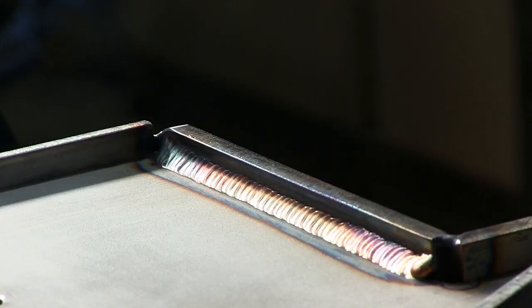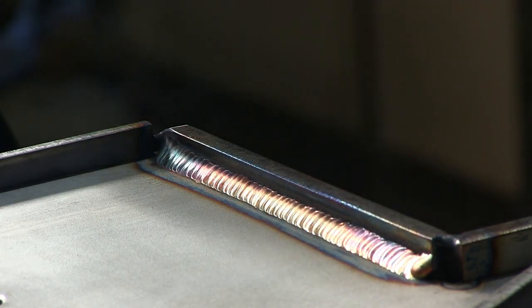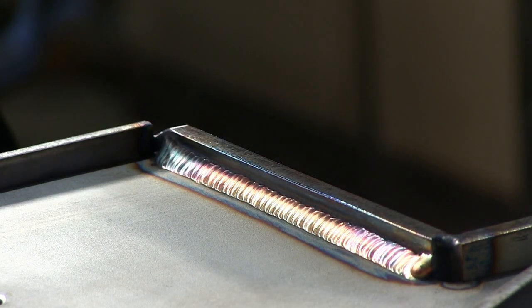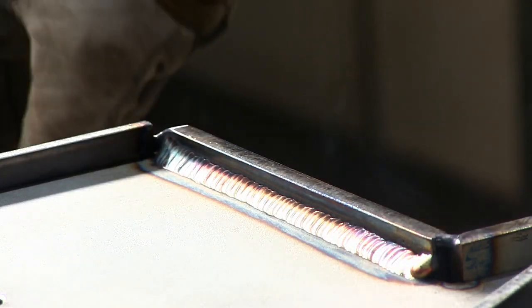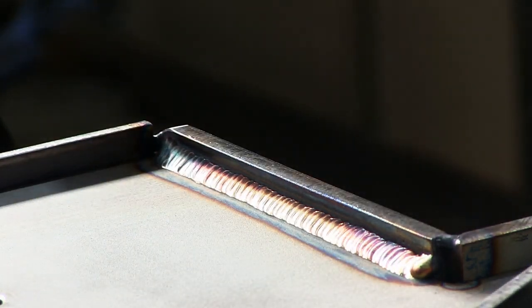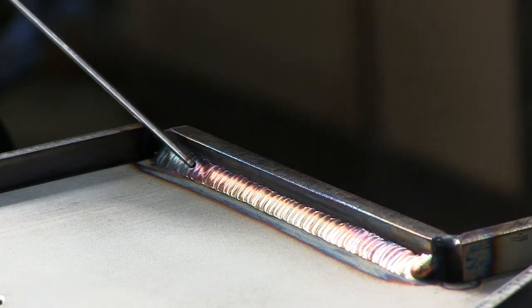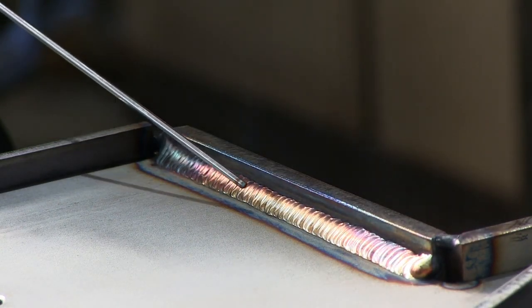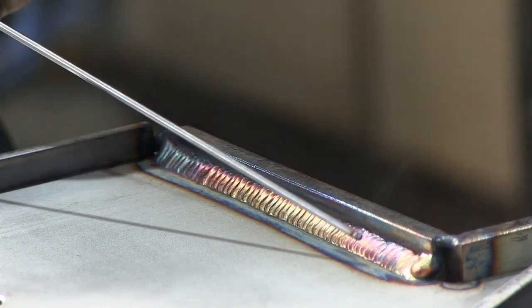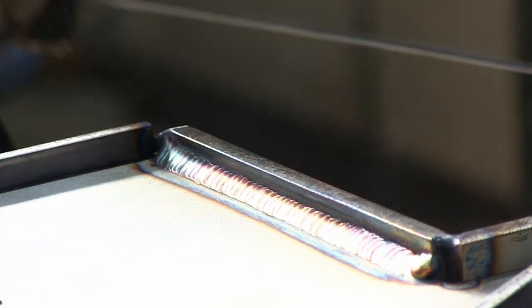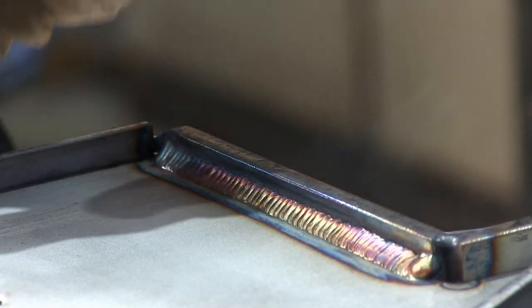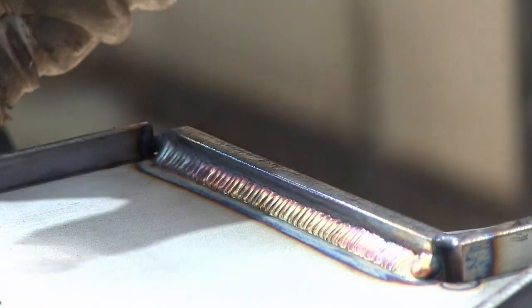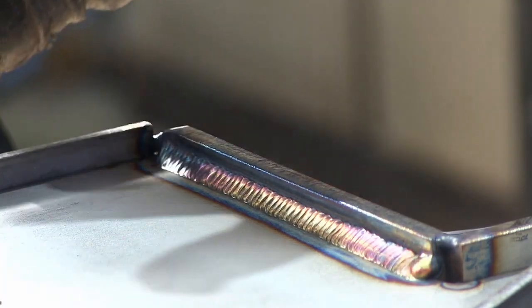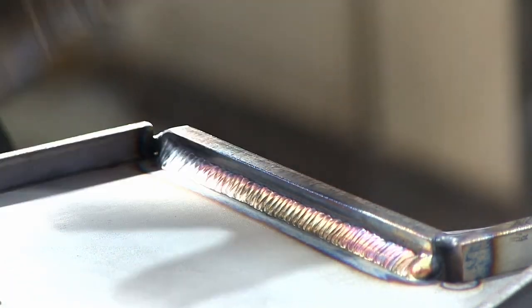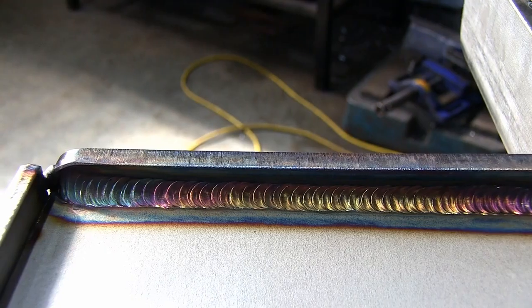It is worth paying attention once we see the final weld to the colors in this weld. You will see that at the beginning of the weld and also at the very end, it will be a more pinkish purplish kind of color, and in the middle of the weld it will be more of a yellowish straw sort of effect, and you will see every single individual dab. Basically, the edges of the weld are corner pieces, so the heat cannot go away as efficiently as it can in the middle.